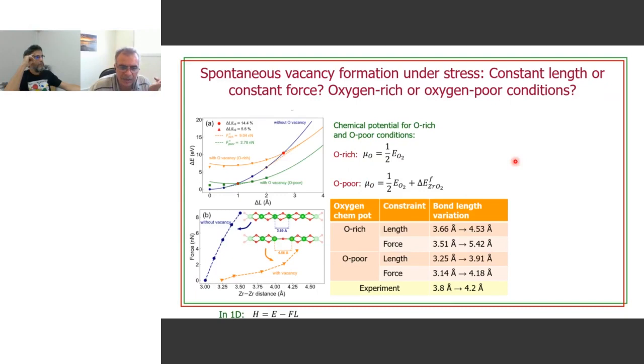But the idea is that we did four different processes. We considered both oxygen-rich and oxygen-poor conditions, and we considered the process happening under different constraints, either constant length or constant force. The only quantity that we had available to compare to experiments is the discontinuity in bond distance between two zirconium atoms as the vacancy is formed. Experimentally, the distance between two zirconium atoms jumps from 3.8 to 4.2 angstroms, and we can calculate the same quantity theoretically using these four different conditions.